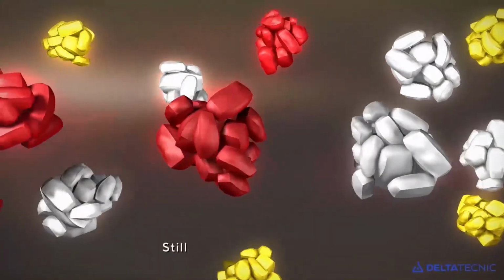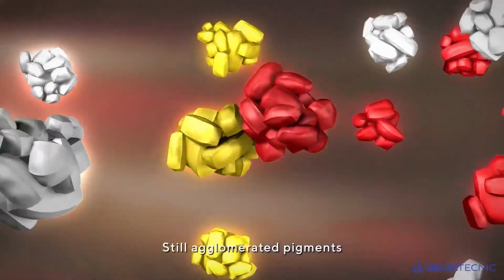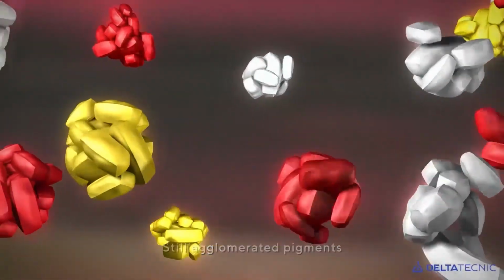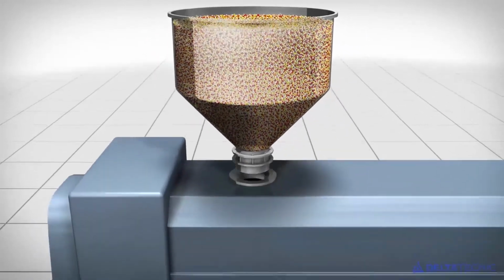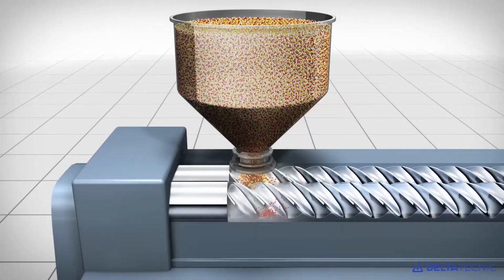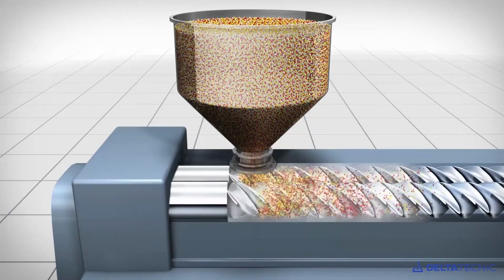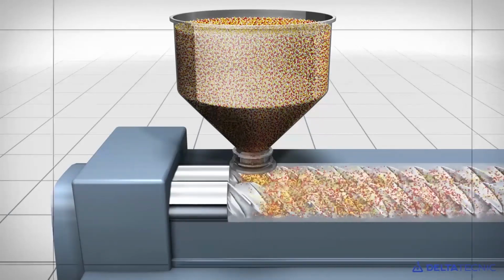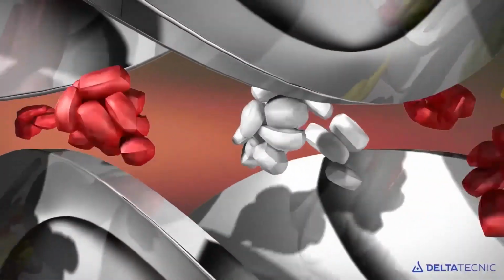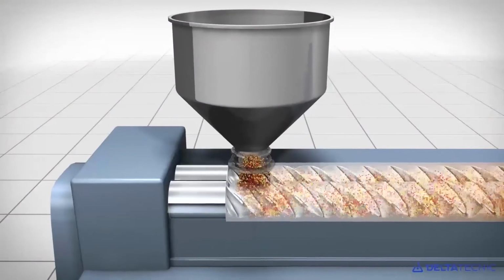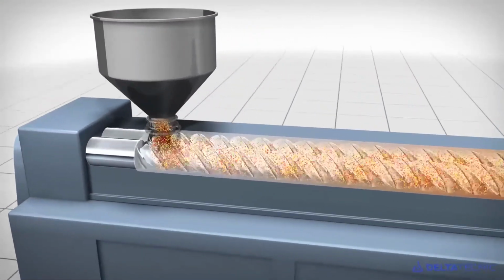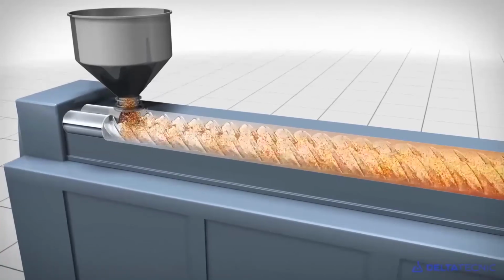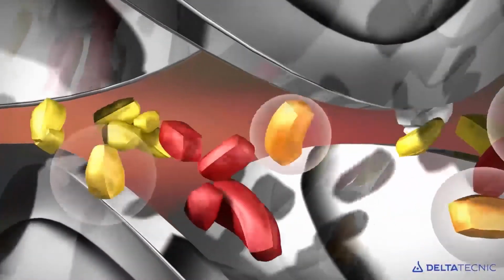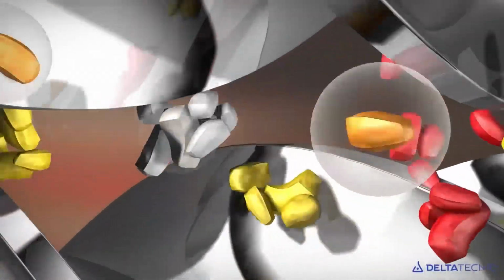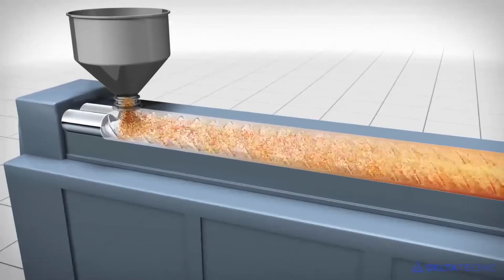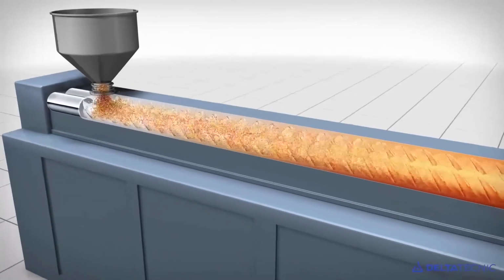In this mixing process, we start to separate those agglomerates somewhat, but the real work of dispersion happens at the extrusion process. So at the extrusion process, with these screws and hammers, we work mechanically on the material, and we separate those agglomerates into single crystal units, and we surround them by the corresponding polymeric base. And this is what we try to represent here with this 3D video. So we separate the single crystal units of the pure pigments, we surround them by the polymeric base, and this is what we call dispersion.